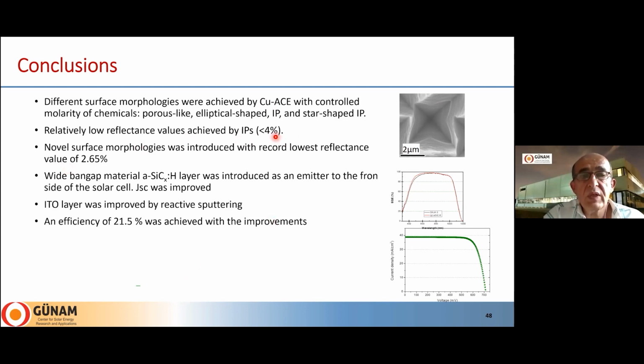So we have reached a value of 2.65% of reflection from such surfaces. Silicon carbide introduction was good for the front side of the cell, so JSC was improved. Then ITO was improved by reactive sputtering, and an efficiency of about 21.5% was achieved with these improvements.